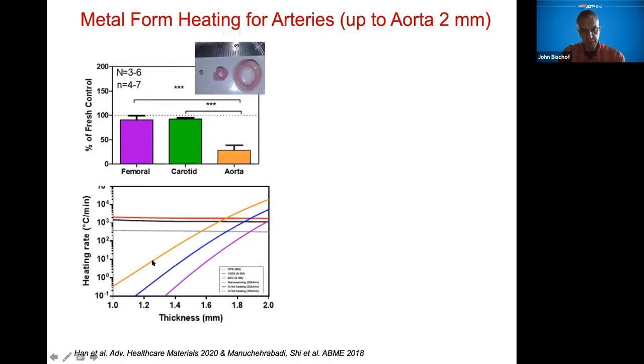So we have DP6, or like 6 molar, VS55, 8.4, and then M22 is 2 molar. So you're going up in concentration and loading. And then you're increasing also here in these more vertical lines. This is going up in heating rate using different technologies with the metal forms as well as nanowarming with magnetic nanoparticles. And you can see over on the right, we are able to actually get to a high viability case if you load the CPA sufficiently and you study the process and the heating.